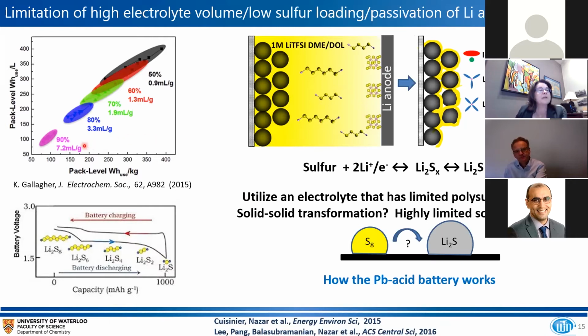So the problem is that if you use a high electrolyte volume to solubilize the polysulfides, you end up with really low energy densities, both at the volumetric and the gravimetric level. And really where you want to be is at a low electrolyte to sulfur ratio, if one can get that. And that means redesigning the chemistry almost completely. So if one could develop, for example, an ionic liquid that has very limited polysulfide solubility and basically trigger a solid-solid transformation, in other words, going from sulfur all the way to Li2S with very little electrolyte involved, one stands a chance of maybe overcoming this problem. And that's effectively how a lead acid battery works. I mean, not obviously with lead oxide.